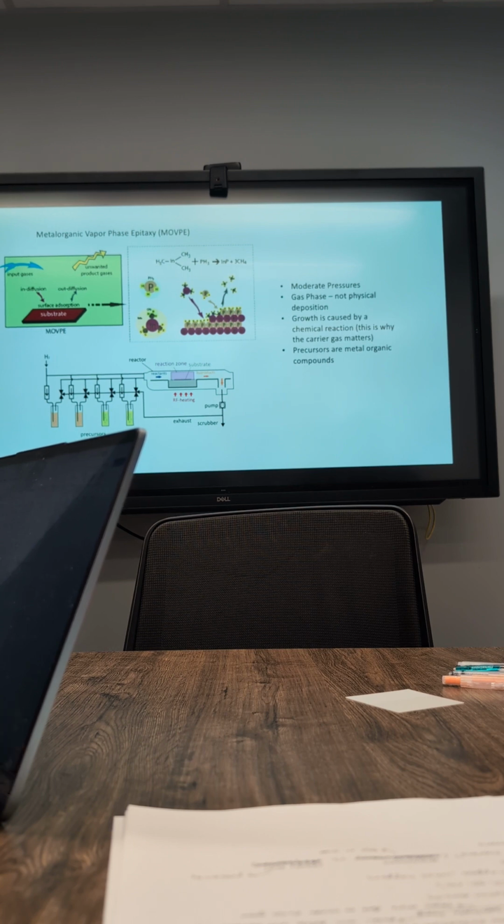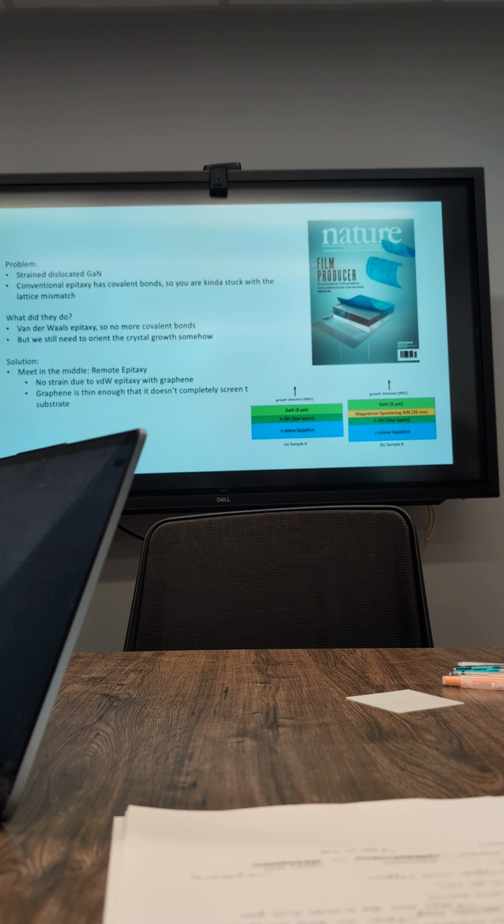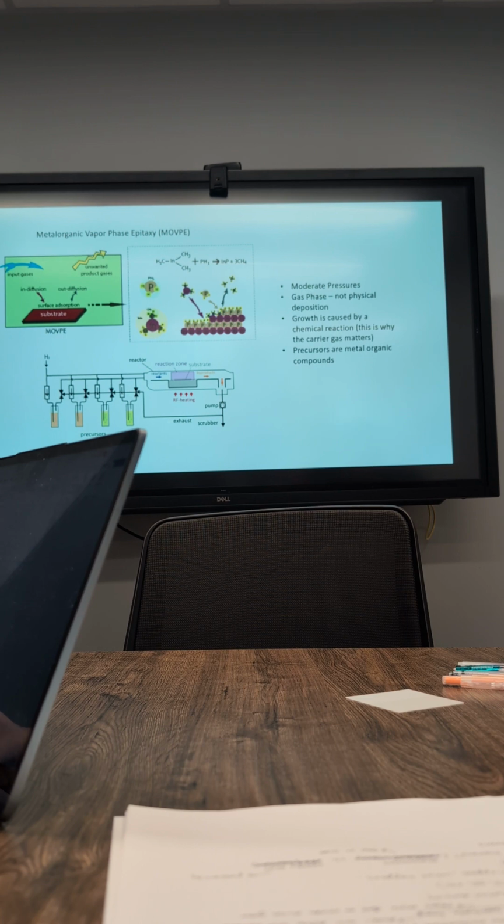So yeah, metal organic CVD. So you have some sort of metals bonded to an organic compound as your reaction. So much higher pressure than MBE. Is that it, that it uses higher pressure than MBE? Yes, it's around ambient pressure, really, like 10 to 760 torr, just because you have all these gases flowing. So the mechanism has nothing to do with it being at a lower pressure or anything. It's that the chemical reaction is happening.